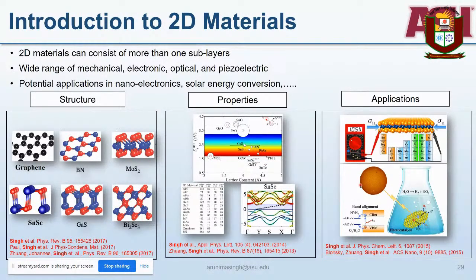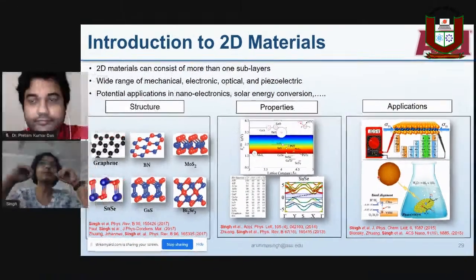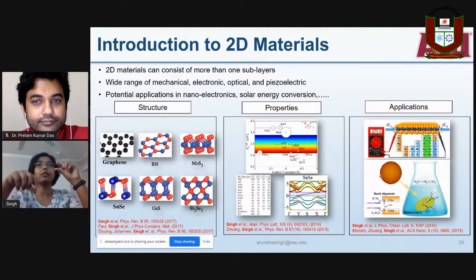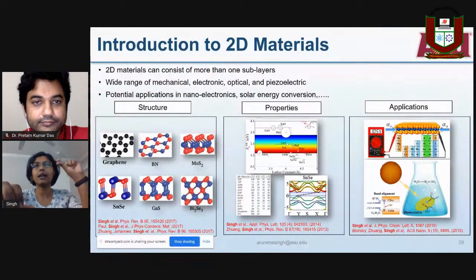2D materials can be defined as materials which are infinite in two directions, but finite in the third direction. And that means two-dimensional materials can consist of more than one sublayer. For example, graphene is a single atom thick honeycomb lattice of carbon atoms. And boron nitride is again a honeycomb lattice, which is single atom thick, consisting of boron and nitrogen. But MoS2 has three sublayers, molybdenum in the middle, and then you have sulfur layers above and below that. And tin selenide has 4 sublayers, gallium sulfide has 6, and so on.